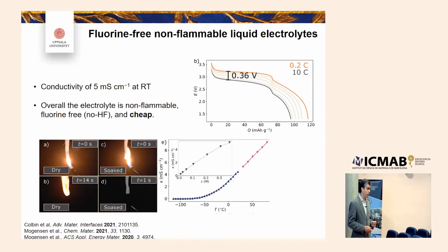But the problem was that we had to use sodium metal as the counter electrode. And we knew that sodium metal is not a good option because you get a lot of side reactions, the electrolyte becomes contaminated, and the results are not reliable.